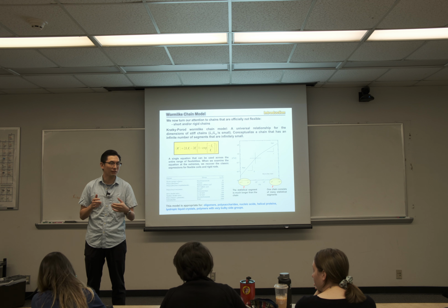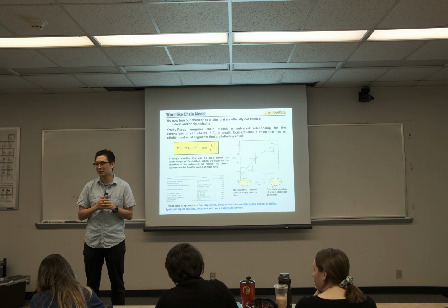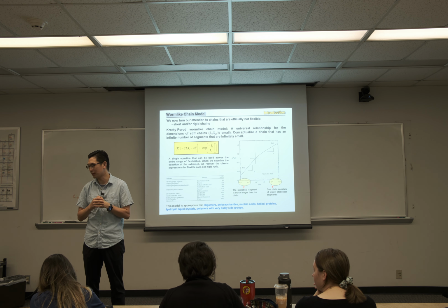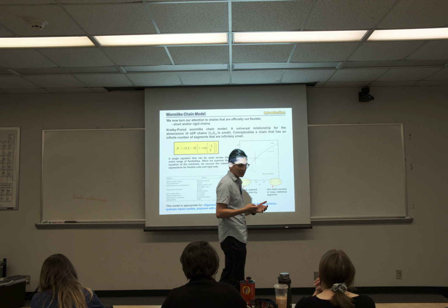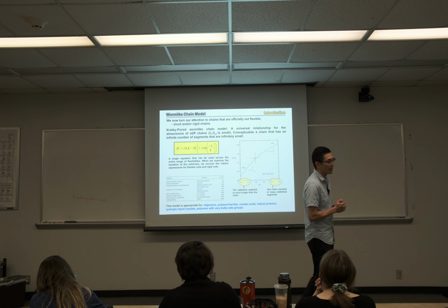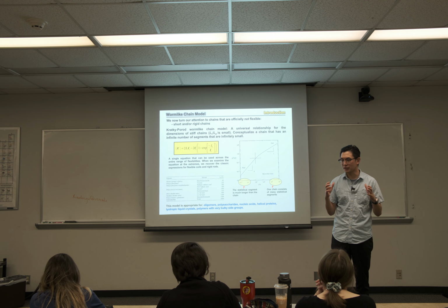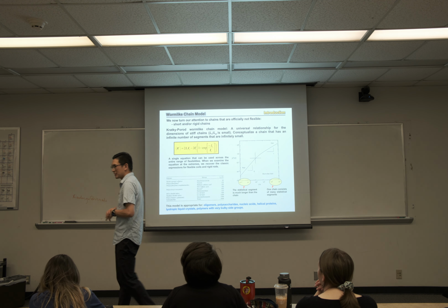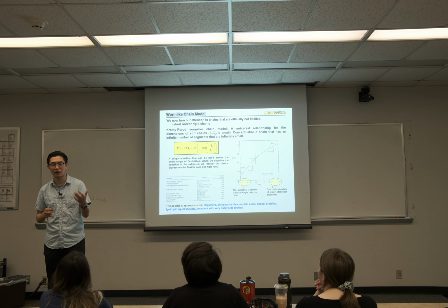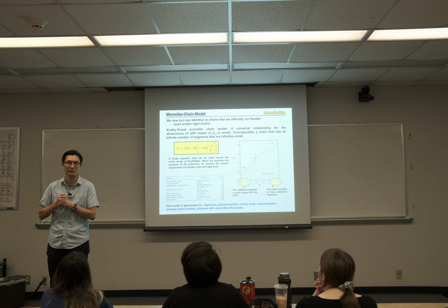We gave a little example of the persistence length for several polymers, such as polystyrene, where persistence length is only about 7 angstrom-ish, so it's very small. Some polymers can be much more rigid, such as DNA molecules, which have a much higher persistence length.